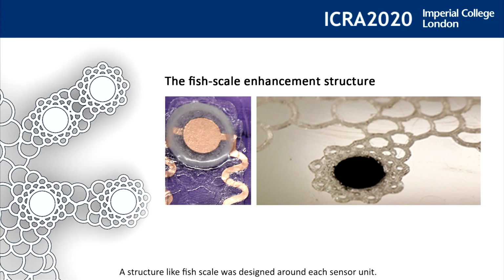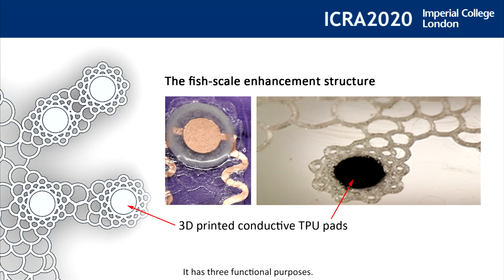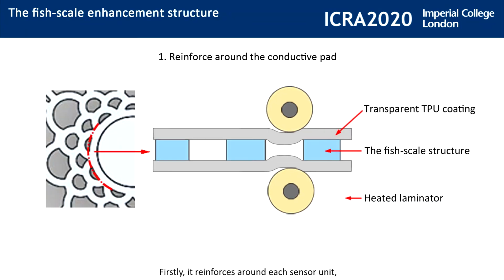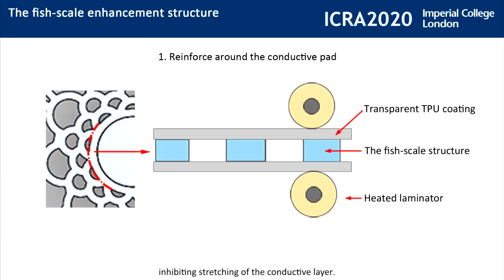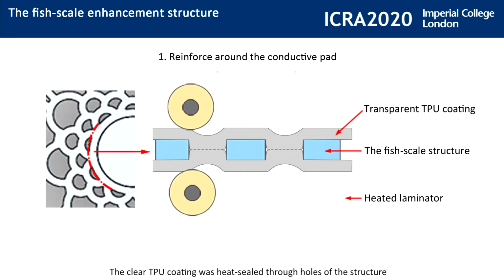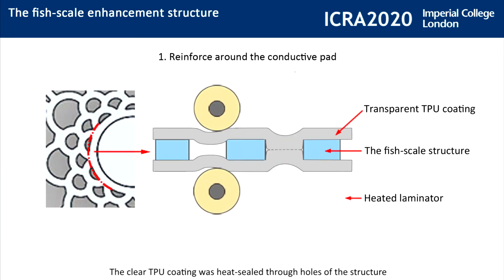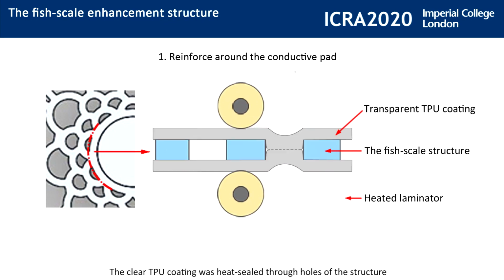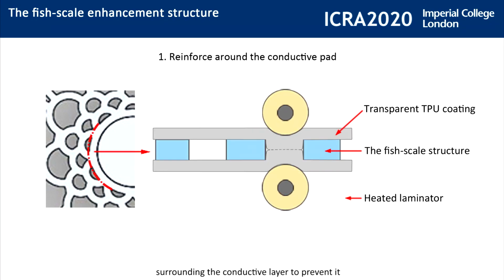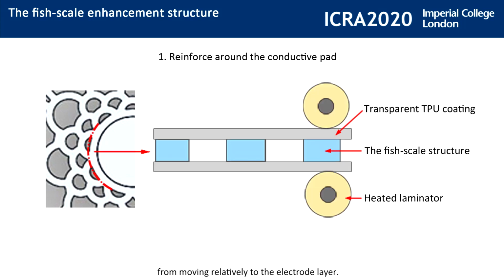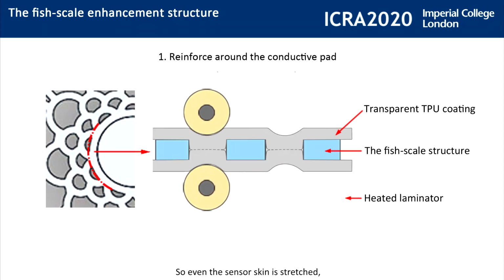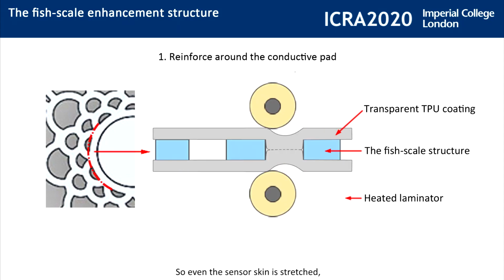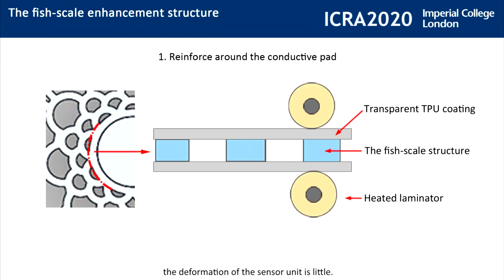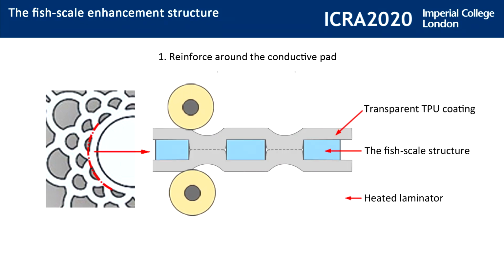A structure like fish scale was designed around each sensor unit. It has three functional purposes. Firstly, it reinforces around each sensor unit, inhibiting stretching of the conductive layer. The clear TPU coating was heat-sealed through holes of the structure surrounding the conductive layer to prevent it from moving relatively to the electrode layer. So even if the sensor skin is stretched, the deformation of the sensor unit is little.